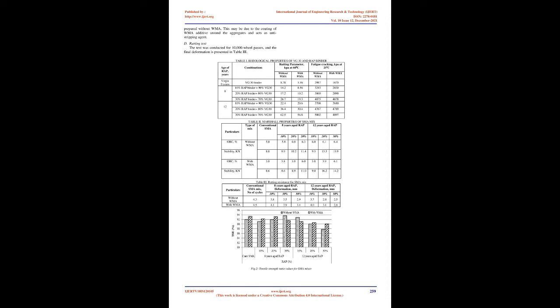A. Rheological properties. The binder rheological properties were evaluated by determining rutting and fatigue parameters at 60 and 25 degrees respectively. The binder rutting parameter, G*/sin δ, should be more than 1.0 kPa and 2.2 kPa for unaged and aged binder samples. Likewise the fatigue parameter, G*sin δ, should be less than 5000 kPa for aged binder. From Table 1, it is observed that the binder rutting parameter improved with increase in RAP age and percentage due to increase in stiffness of binder.